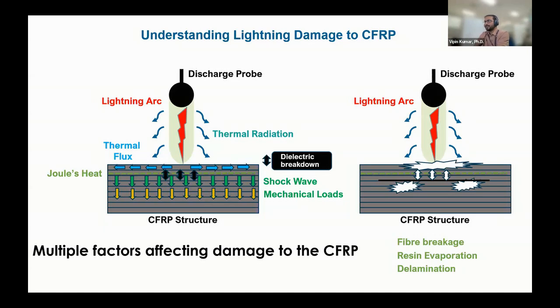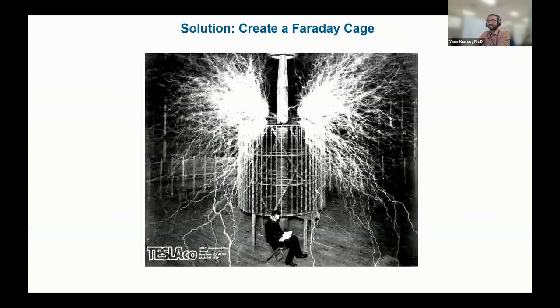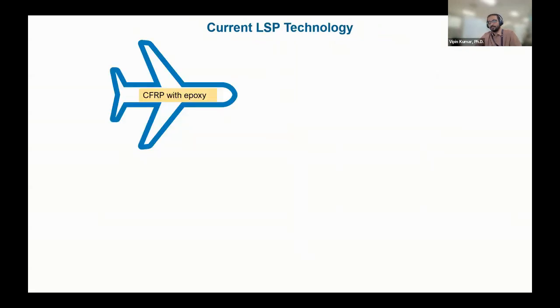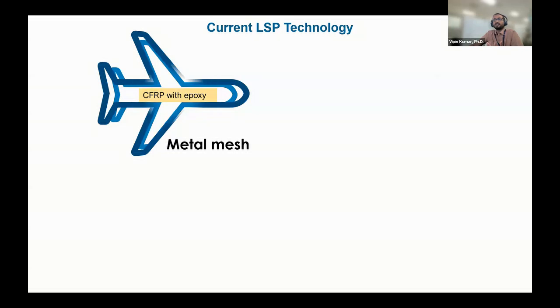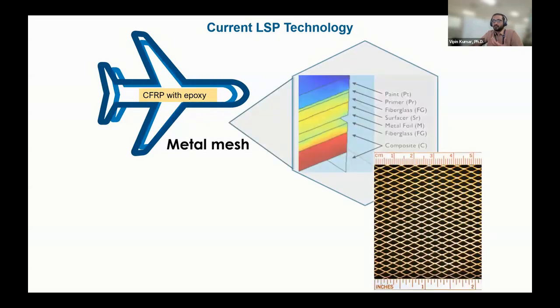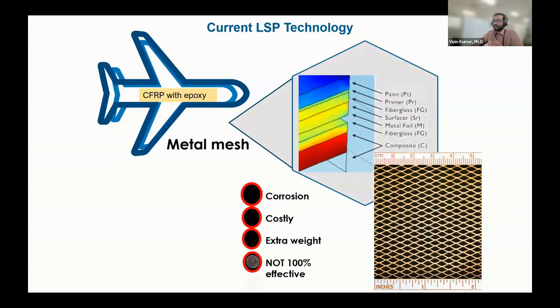So what do aircraft companies do right now? They go back to basics. One solution is to create a Faraday cage around your structure so that the current doesn't go inside. If you have a conductive component outside, the current stays outside. So that's what the current methods look like. If you have a composite aircraft, you cover or put metal mesh around the critical areas which get hit by lightning more often, for example the nose and the wing edges.